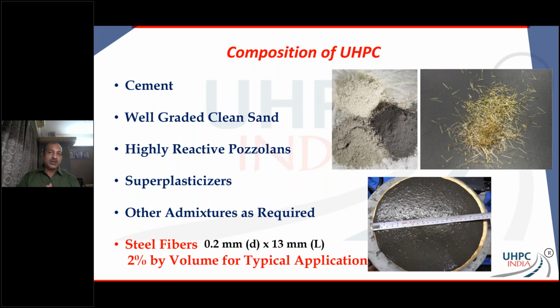But of course, one of the main other ingredients is your microfine steel fibers. So top right, you can see the picture of the microfine steel fibers, but bottom left, you see the size of the steel fibers. Now these 0.2 mm by 13 mm lengths of steel fibers are very smooth, very high tensile steel fibers, about 2800 MPa tensile strength steel fibers. If you add somewhere about 2% by volume, which is about 156 kilograms per meter cube, you get extraordinary behavior in not only tension, but you get extraordinary behavior in shear as well, right? And we're going to see that.